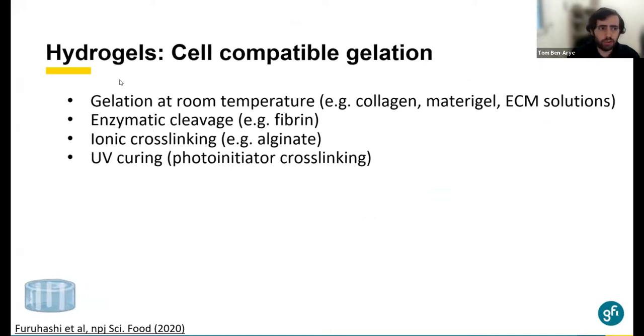So several ways to polymerize gels in cytocompatible manners are gelation in room temperature. There are some materials that can be liquid in low temperature, around 4 degrees. And when we heat them up to room temperature, they polymerize and form gels. This could be Matrigel, collagen, some other extracellular matrix solutions. And the issue with those is that they are not food grade or they are expensive, but perhaps we can find other alternatives for gels that can undergo gelation at room temperature compared to 4 degrees. We can find some materials like that from bacteria, from microorganisms, or from plants, that could be very valuable for some kind of a hydrogel for tissue engineering for cultivated meat.